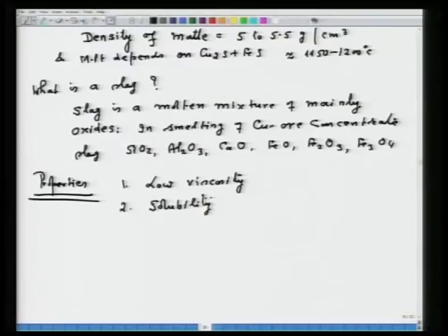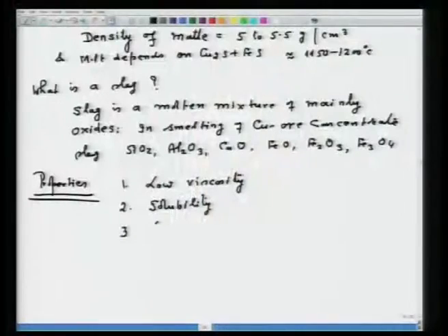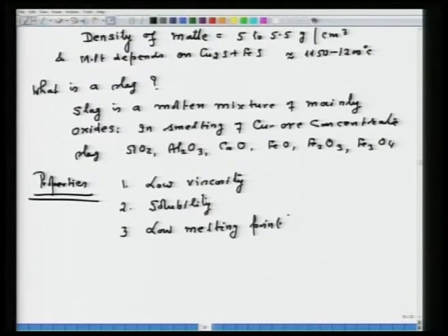That means slag should be able to dissolve the oxides which are being separated during smelting of ore concentrate. That is an important thing: you have to make a slag of such a composition that the oxides present in the ore concentrate are dissolved, and you form a liquid. It is a homogeneous liquid solution, rather a molten solution. Third important property, it should have a low melting point, because you will not go more than 1200 or 1300 degrees Celsius. So, at that particular temperature, the oxides which are being separated from the ore concentrate should be able to dissolve and they should be liquid.